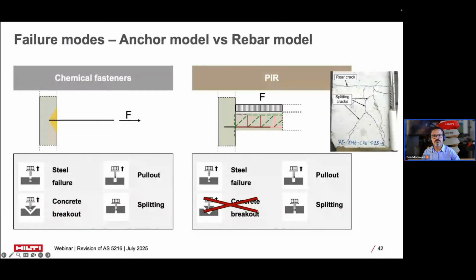The failure modes for chemical fasteners include steel failure, pull-out failure, splitting failure, and concrete breakout failure. But in the rebar model, we only have steel failure, pull-out failure, and splitting failure modes. In this model, concrete breakout is restrained and doesn't develop. So that's the only difference between these two methods.